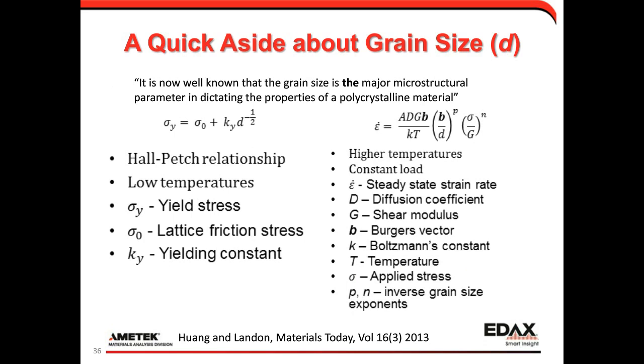So in this case, I just wanted to take a quick moment to talk about grain size. This is a great quote from an article in Materials Today a few years ago, where it says, it's well known that grain size is the major microstructural parameter in dictating the properties of a polycrystalline material. These are just 2 different equations. The one on the left is your Hall-Petch relationship, which gives an idea of how the yield stress is influenced by the average grain size. The one on the right gives an idea of the steady-state strain rate, where grain size is a parameter. By knowing the grain size, we can correlate that to a lot of different material properties, and EBSD is a nice tool for measuring that.